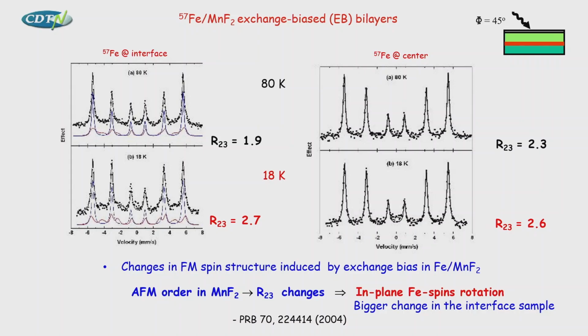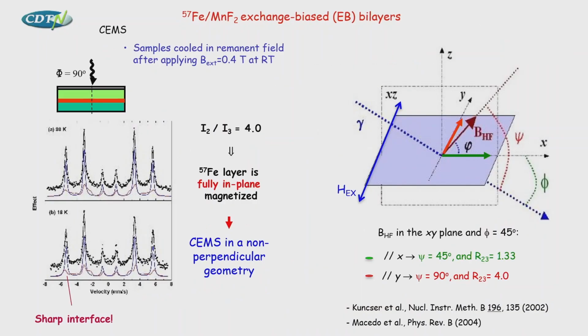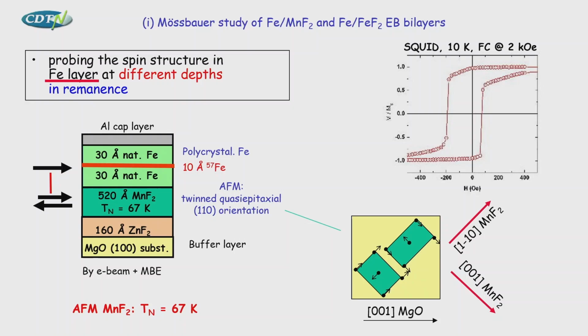So did you take this into account? No, this is a slide I took away. What we see is that the spins are in plane. We apply the field in this direction, and as soon as there is coupling, the spins in the antiferromagnetic layer are pointing in this direction. The spins at the interface in the antiferromagnet are pointing in this or that direction. That means the ferromagnetic iron layer is coupled within these two directions. This is why you do not expect a huge change in the strain due to the temperature difference.